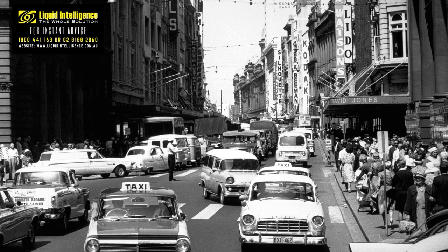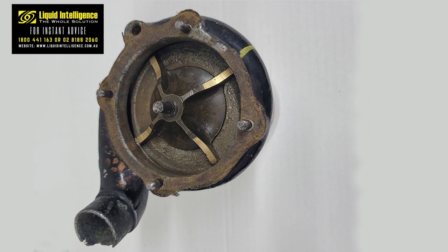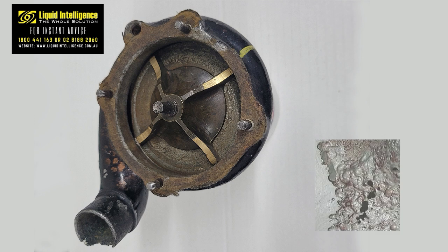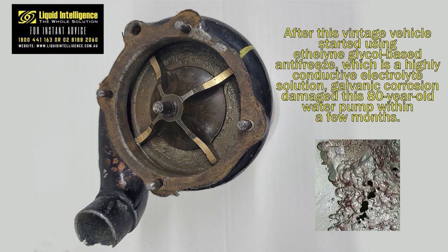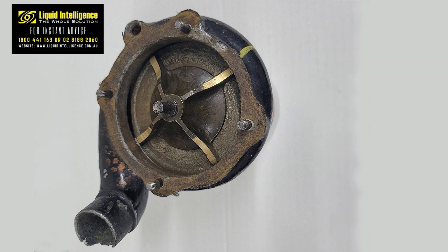Here is a good example of why that is the case. Consider this well-made vintage 1940s cast aluminium water pump with a copper impeller. Cast aluminium, being an anodic metal, has very low nobility and is less resistant to galvanic corrosion, while copper, a cathodic metal, has high nobility and is more resilient to galvanic corrosion. This wasn't a problem when the vehicle used water or soluble oil as a coolant, as they both had very low conductivity. However, after the vehicle started using ethylene glycol-based antifreeze, which is a highly conductive electrolyte solution, galvanic corrosion damaged this 80-year-old water pump within a few months.